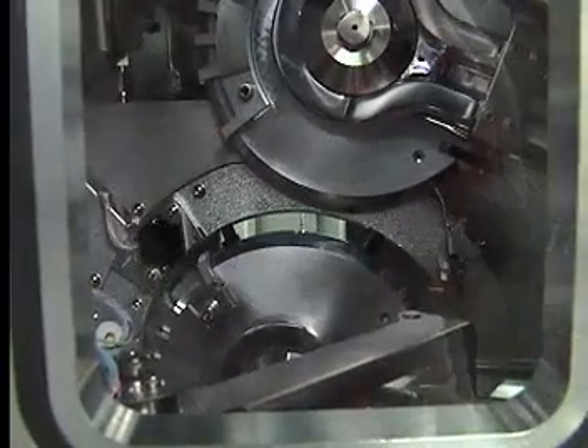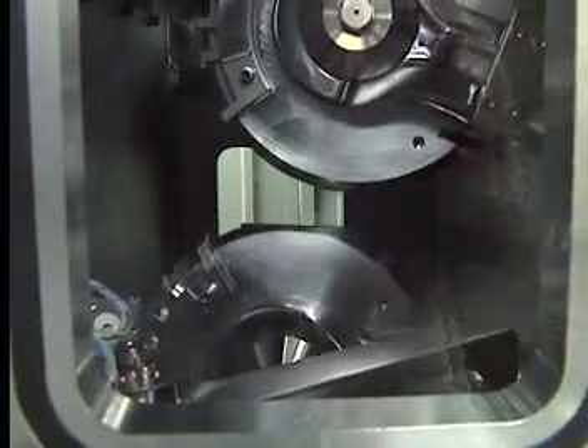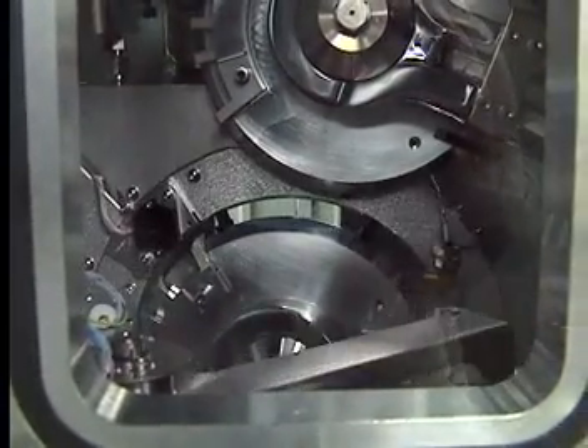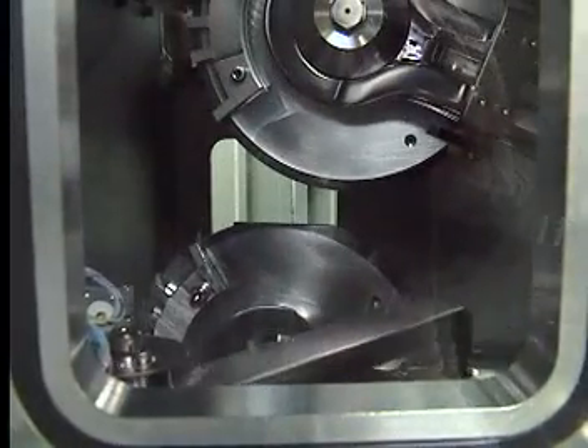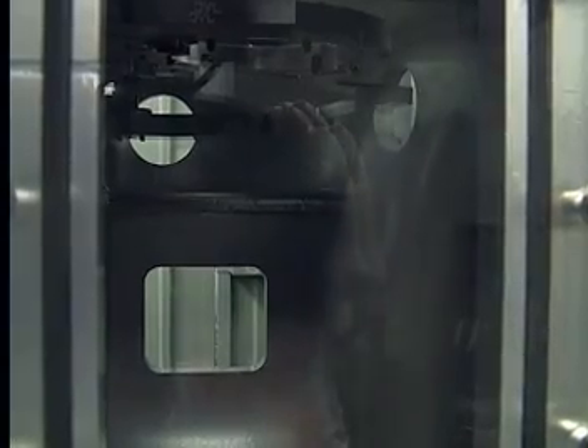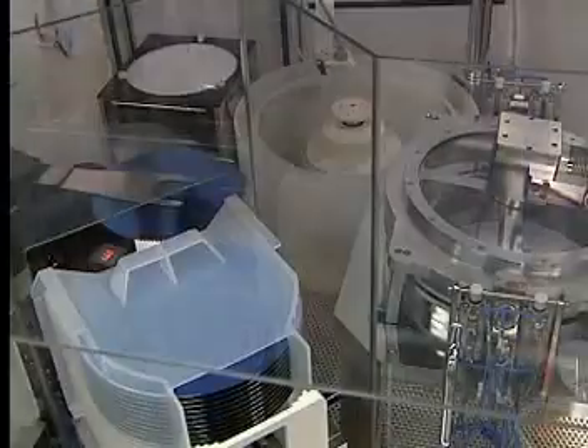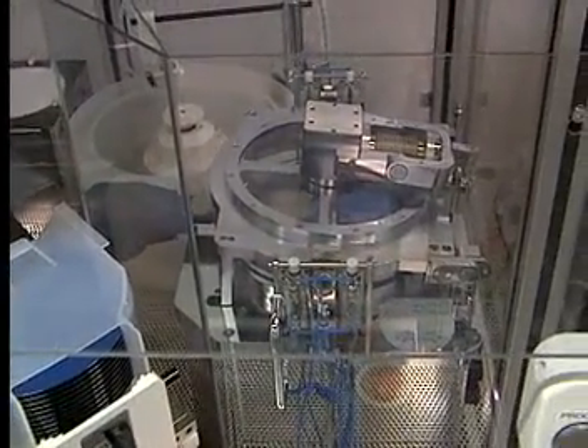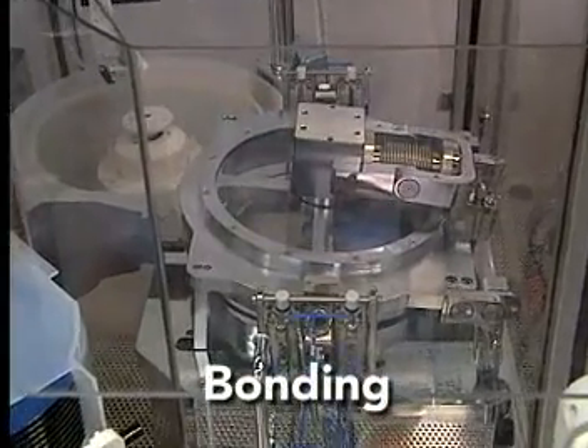This implanted layer forms the fracture plane, which separates the top silicon and BOX layers from the donor wafer and allows the transfer to the handle wafer. Thus, the thickness of the top silicon layer in the finished SOI wafer is determined by the energy of the implanted ions. The donor wafer is now ready to be bonded to the handle wafer.